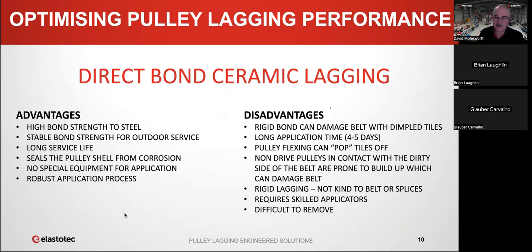Advantages and disadvantages of direct bond. Advantages: high bond strength. It's the highest of any of the different lagging bonding systems. Very stable bond strength for outdoor service. Direct bond pulleys can be in service for more than 10 years. The adhesive seals the pulley shell, prevents corrosion. You don't require any special equipment apart from the stands that you saw those pulleys on, and the process is very robust. The disadvantages of the direct bond is that because it's a rigid ceramic, it can damage the belt.